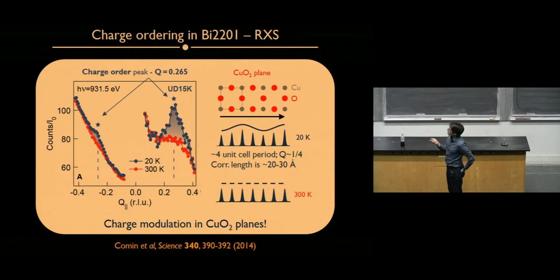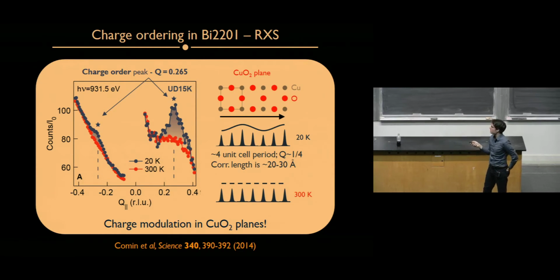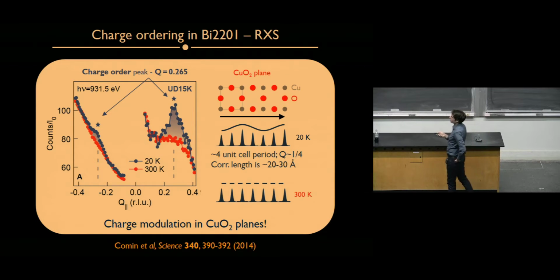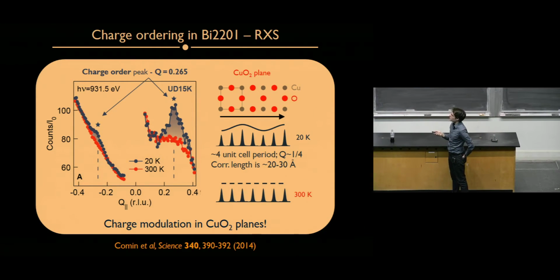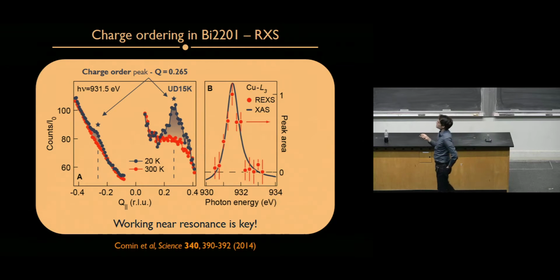Okay, it's a very hard measurement. As you can see, this is a very weak peak in reciprocal space. Typically, these things, if you do Bragg crystallography, if you do crystallography in general, are extremely sharp. This is very broad, and it's very hard to detect, but it's there. So it's a challenging experiment, but it's there. And the only way to see it is if you tune yourself to the resonance.